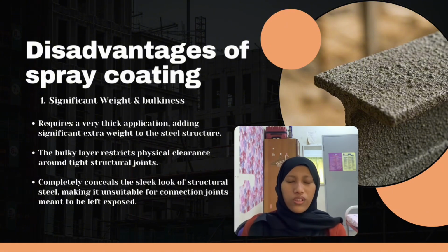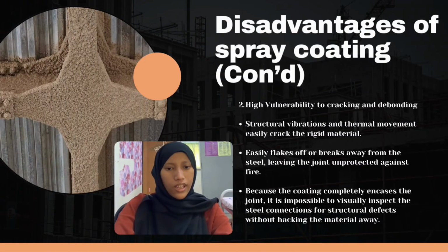It removes the sleek look of structural steel, making it highly unsuitable for connection joint elements to be left exposed by the architectural design. Moving on to our second point, high vulnerability to cracking and debonding. For this point, as we all know, buildings are not static, they move. Structural vibrations and thermal movement can easily crack this rigid material over time, and when it cracks, it can easily flake off or break entirely away from the steel, leaving critical joints completely unprotected against the fire.